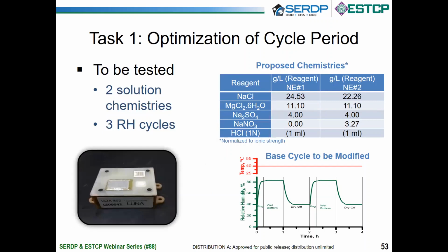So task 1 for this effort is to test a total of 6 different environments. And how we've split those up so far is to test 2 solution chemistries and 3 relative humidity cycles. This will be done mainly to identify what are the controlling chemical species in the solution chemistries that mandate or offer different corrosion severity or attack morphologies. Also, the 3 relative humidity cycles will do the same, and hopefully we'll be able to get a better idea about what exact parameters in terms of the relative humidity cycles control the mode and extent of corrosion that we're seeing.